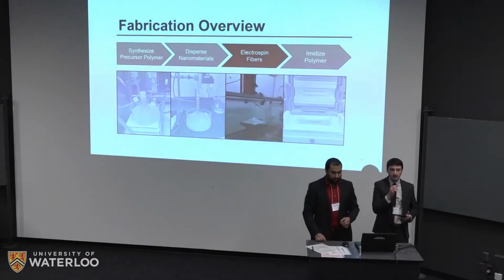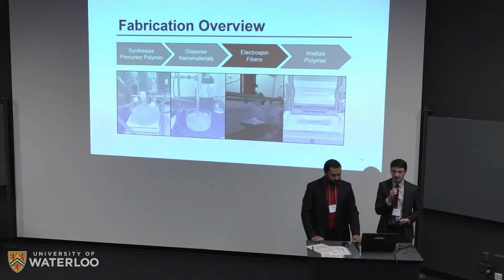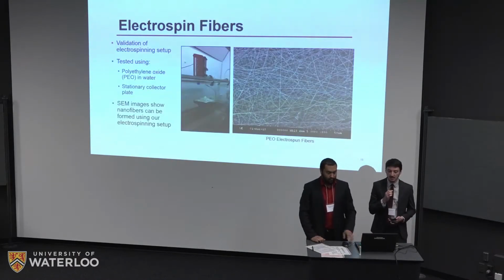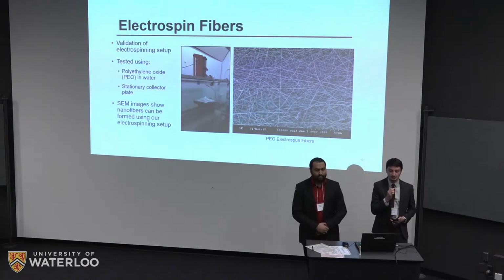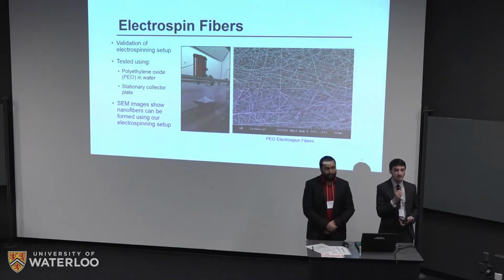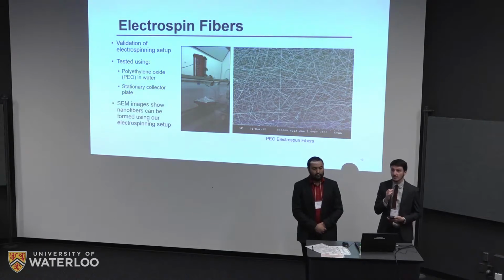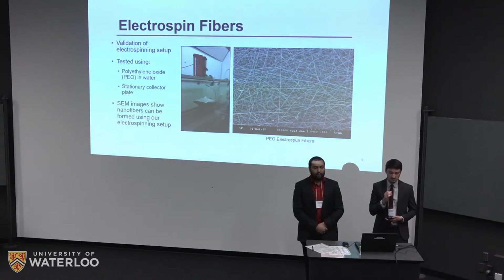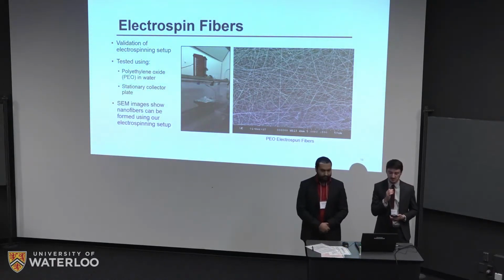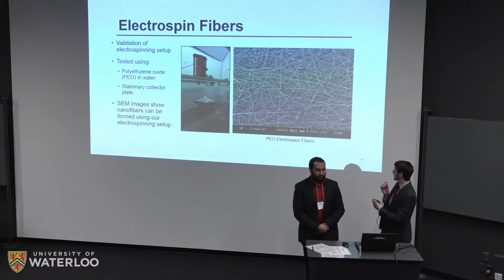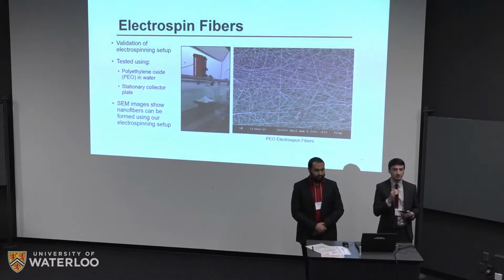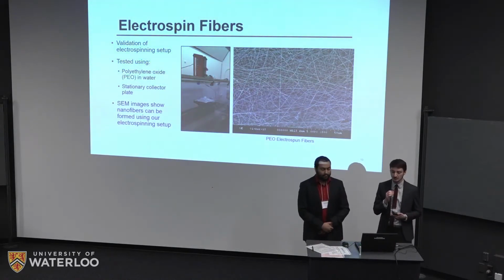So once we processed our precursor polymer and our nanomaterials, we then proceeded with electrospinning. In order to validate our electrospinning setup, we used polyethylene oxide and water to make sure that we can produce fibers with anything. We were able to get very nice fibers from our electrospinning setup, as you can see here. This is an SEM image of PEO fibers that we made, and this verified that we can use our electrospinning setup correctly.